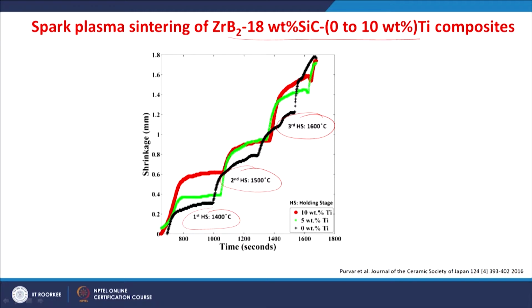Now, in general we can see there are 3 stages of shrinkage increase corresponding to sintering stages. So, first, in general the rate of the shrinkage is lower in the first stage and a bit higher in the second stage, and the shrinkage rate is very aggressive in the third stage. With respect to composition, now you can see when the titanium was used, shrinkage was higher, particularly in the first and second stages.